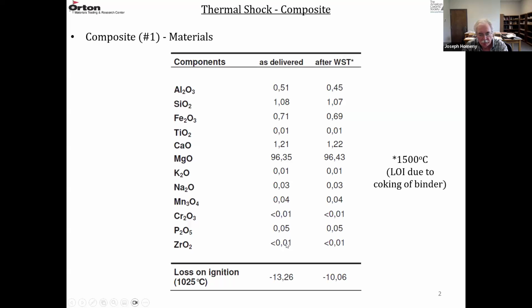So this was the chemistry of the material that was looked at. It's about a 96% MgO material. This is the chemistry of the oxide, and then the loss on ignition indicated there was 13% carbon present. That's as delivered. The carbon is usually a combination of flake graphite and the resin, which is usually a phenolic resin. This is after the wedge splitting test, and that was at 1500 degrees C.